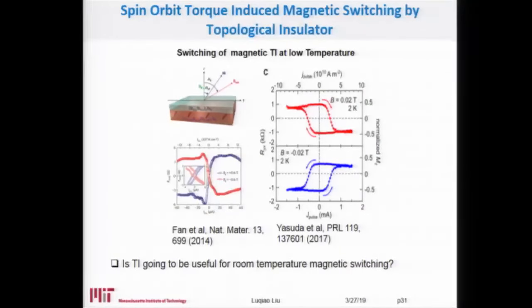Actually, this was proved a few years ago in experiments where people demonstrated that at a very low temperature, 2K or 4K, you can utilize the surface states of topological insulator to switch some low temperature magnetic materials. Here it is some magnetically doped topological insulator, bismuth antimony telluride. People show that by applying current inside the topological insulator, you can switch the magnetic moment orientation in this magnetic layer. However, those experiments are only done at very, very low temperature, as I said, 2K or 4K. The question is, is it possible to push this effect to room temperature and then realize some more practical spintronic device?